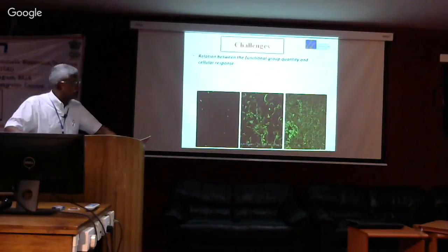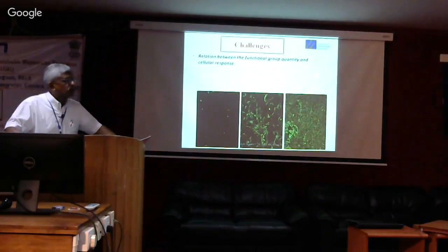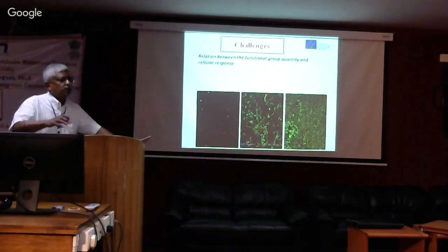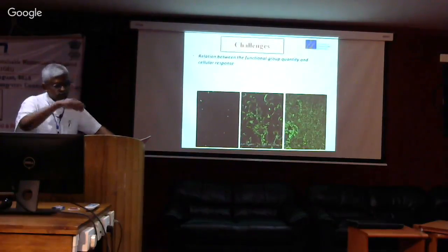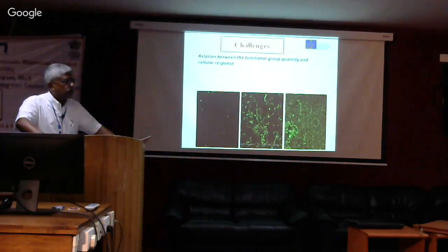The challenge with polystyrene was that it is so hydrophobic that putting functional groups became the limiting issue. So calculation would suggest that you may get, let's say, 5 milliequivalents per gram. We were able to get only 1 milliequivalent. So we did try polystyrene as well, but because our success was so limited, I will not show you any data. Work is still